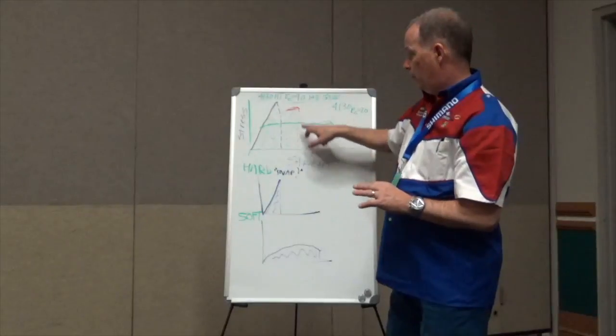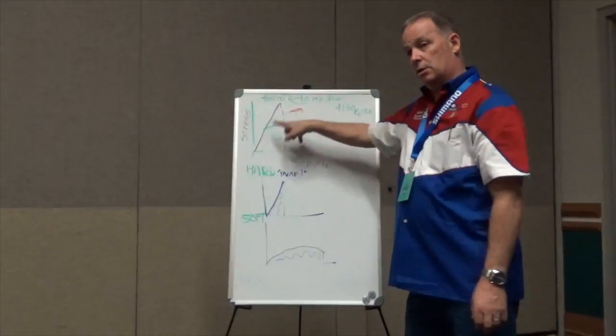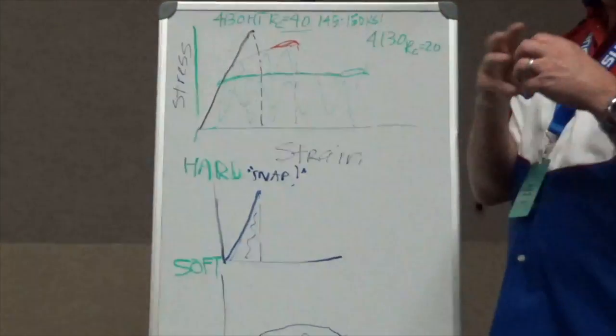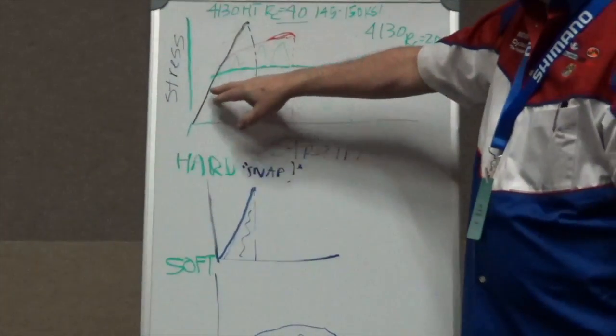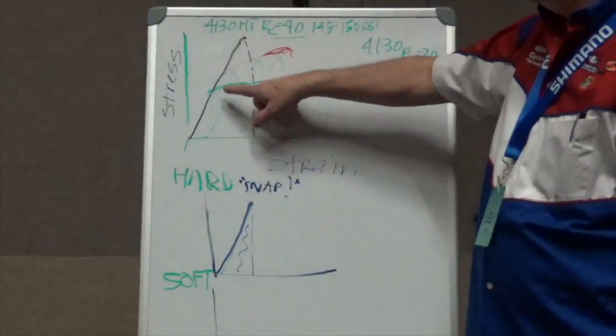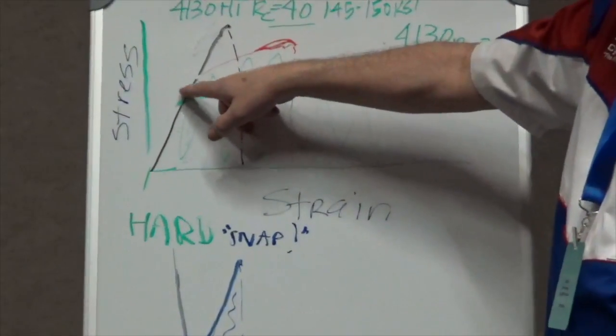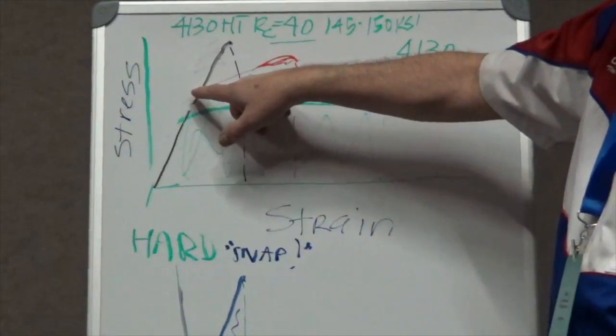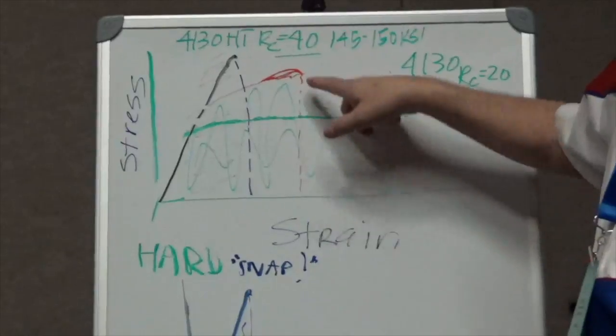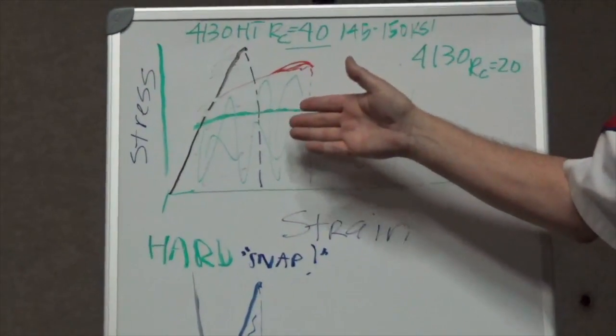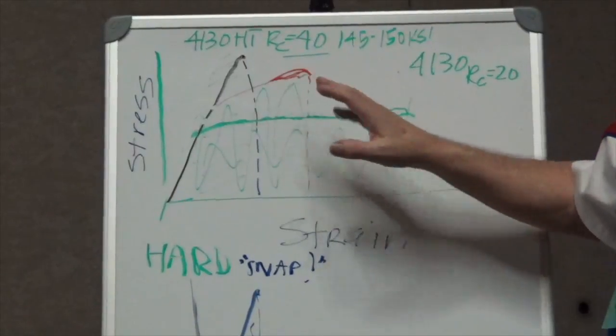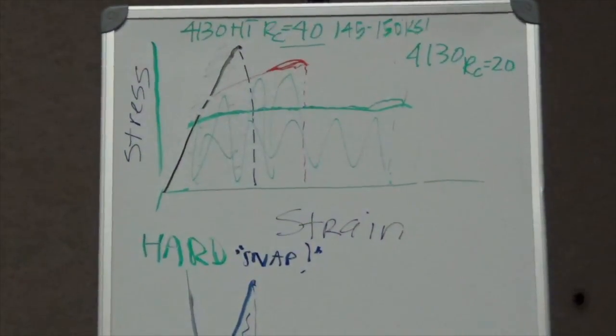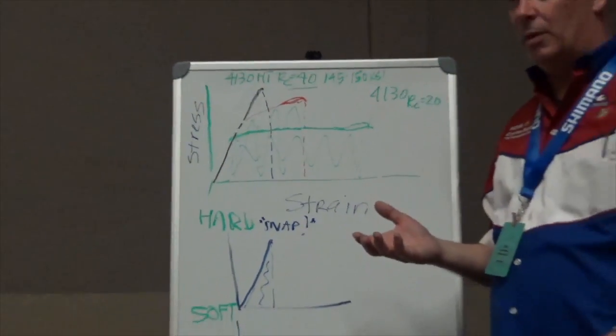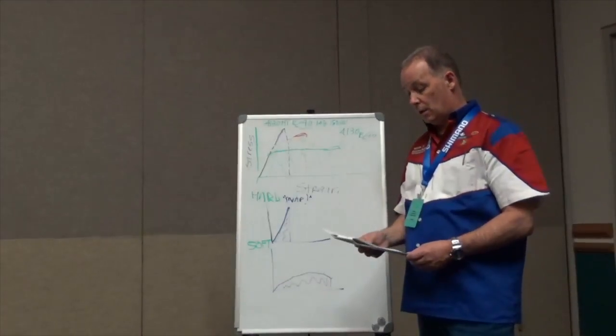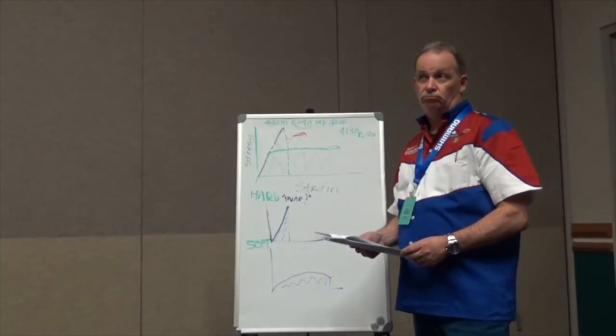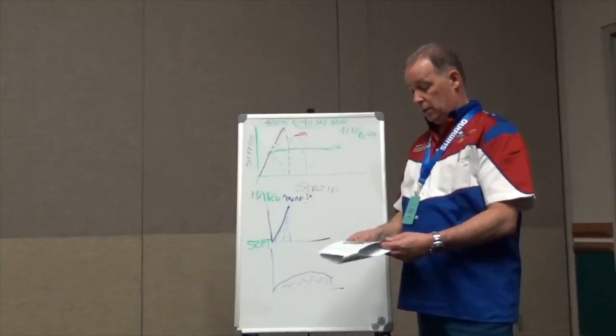So what we're looking for here, for instance in a bicycle tube, which is pretty well evolved if you think about it, is normally you're going to cold work a tube, and that's going to give you a certain amount of additional hardness, let's say in here somewhere, and then you're going to try to do, let's say, a mild heat treatment, and that's probably, for instance in chromoly, going to give you the optimal result. Depending on the alloy, some of the alloys are harder to begin with, and you don't have to do as much with them. In fact, you're better off if you don't. They'll actually be more tough, there's that word again, if they're not heat treated.